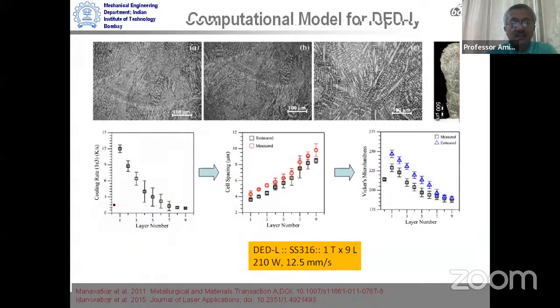Not only that, these kind of models can also provide us very useful information. It can provide us information like layer by layer variation in the cooling rates. It can provide us information of layer by layer variations in cell spacing, which can be correlated with variations in mechanical properties as we print the layers one after the other. And if these models can be verified with experimental results, they can predict things more reliably, and perhaps this can reduce a lot the number of trial and error experimental studies.